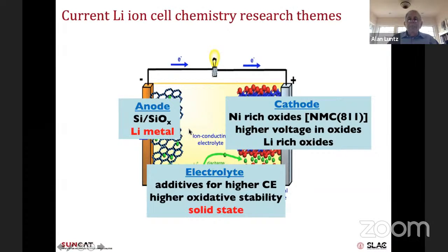On the cathode end of things, typical cathodes are lithium nickel manganese cobalt oxide, for example. That's one of the best cathode materials. And there's a tremendous push throughout the industry to get rid of cobalt as much as you can, because that's the most expensive item in the cathode and in the battery in general. Also, there are a lot of ethical problems about how it's mined. So most batteries right now have either 30% or 20% cobalt in them. There's a lot of interest in trying to push in the short term to 10% cobalt, 10% manganese.